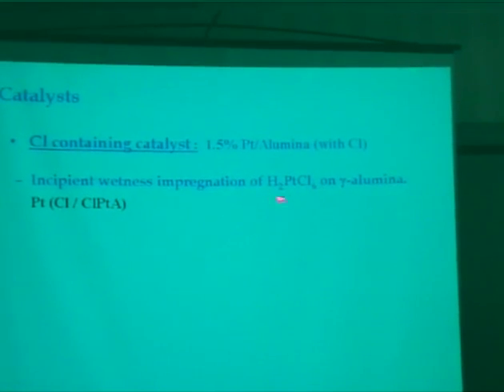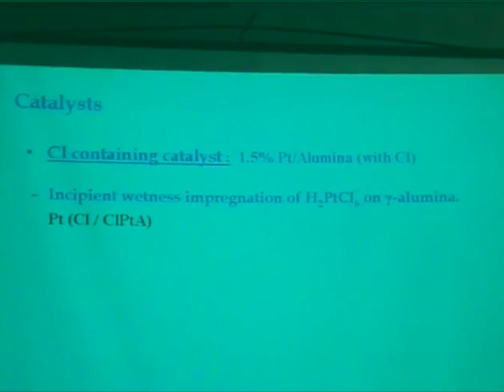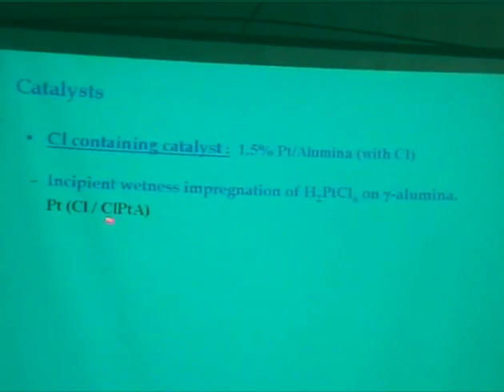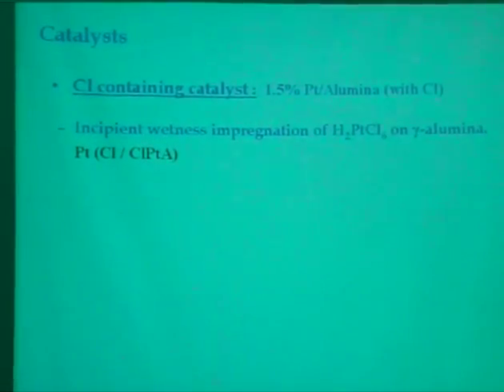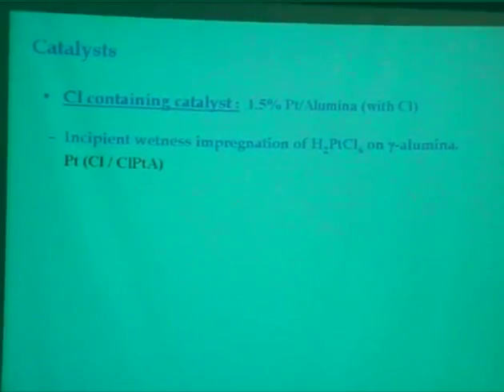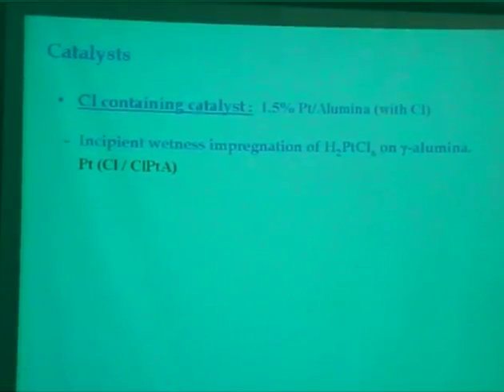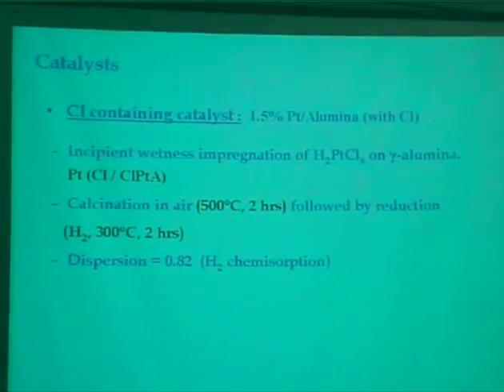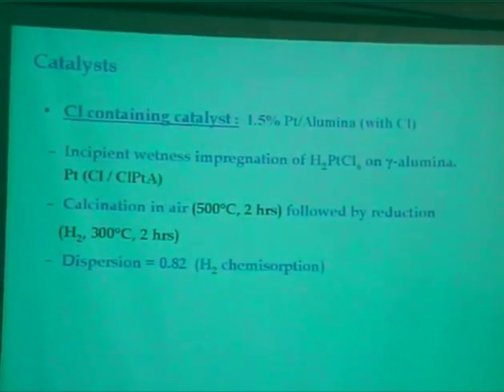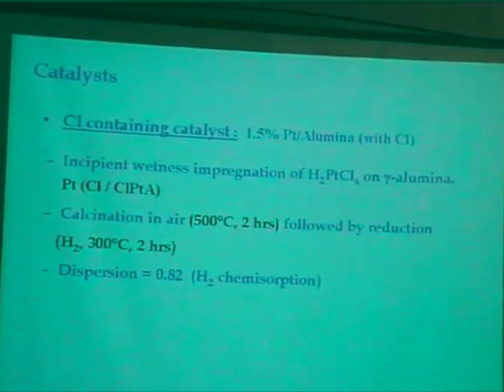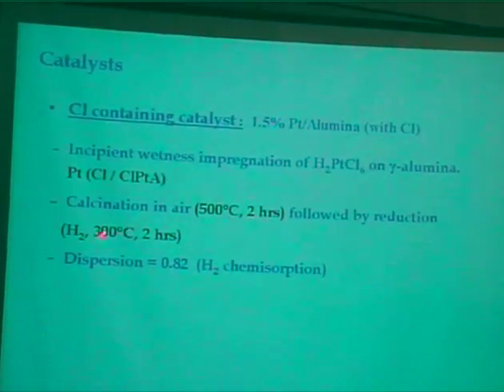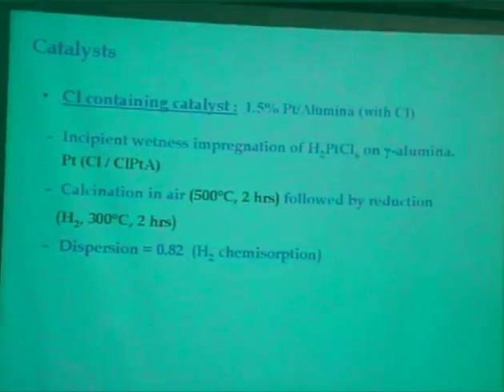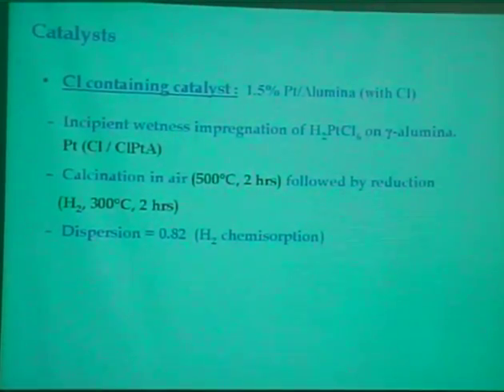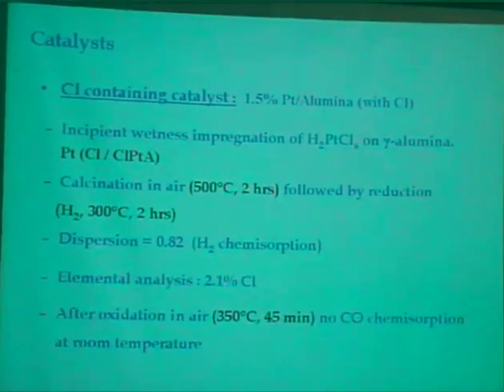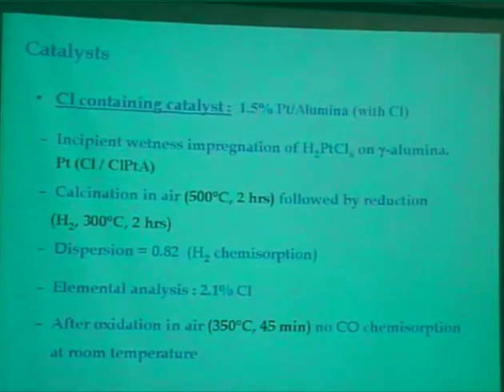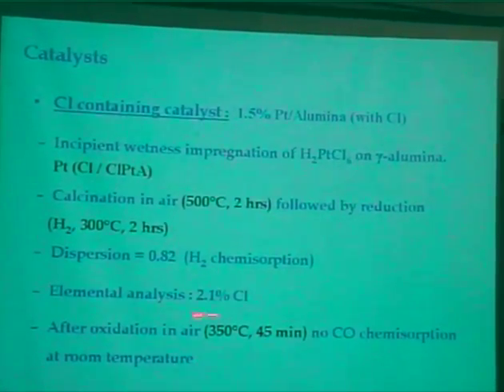The other catalyst was prepared with chloroplatinic acid on gamma alumina, and we're going to call this the chlorine-containing catalyst. To demonstrate some of these effects, we have also prepared catalysts in which we added HCl in order to introduce chlorine. Now, it turns out that chlorine had a good effect on preventing sintering. We want to maintain very high dispersion. You can do that with the chloroplatinic acid, but not with the other catalysts. We reduce it, and we are able to get pretty high dispersion with this catalyst. This is not the case, for example, if you're working with silica. So all these things have to be accounted for when you're doing these reactions.